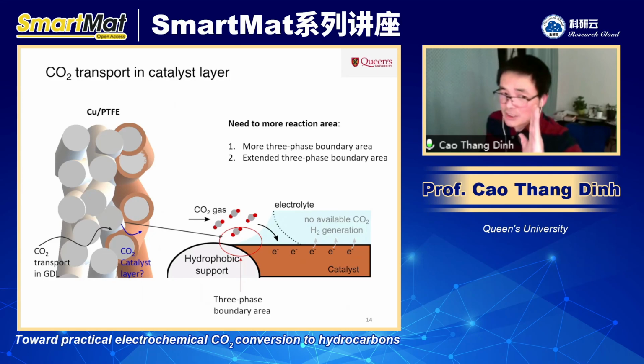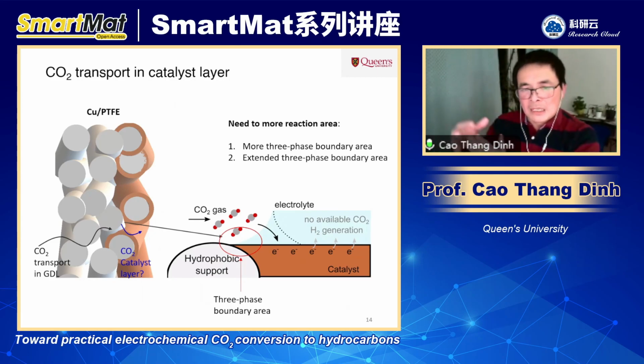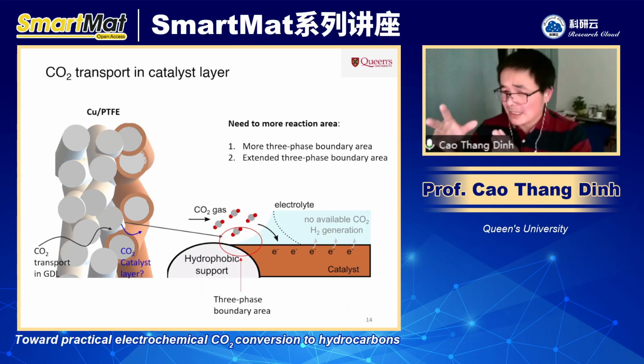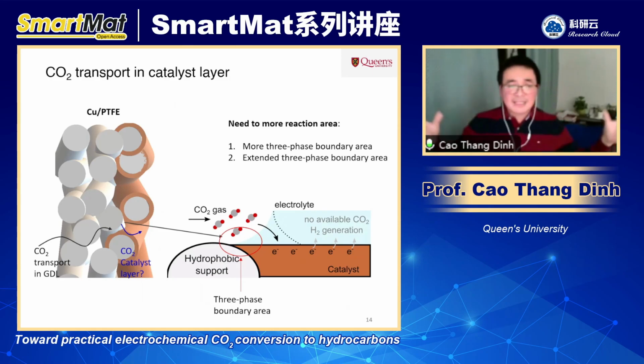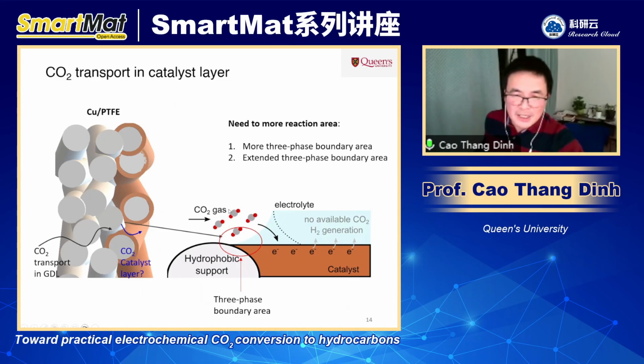Inside the catalyst layer, it just stays there, especially when you use a basic, alkaline electrolyte, right? The basic solution and the CO2, which is an acid gas, just combine together, and it converts the CO2 into carbonate. So you cannot convert the CO2. As you can see in the figure on the right-hand side, the CO2 in the gas phase can be converted on the copper near the PTFE, but it cannot be transported to the area far from that interface, because the CO2 will be converted to carbonate before it can be converted. So with this structure, only a small portion of the catalyst can be used, and the majority of the catalyst is not accessible to CO2.